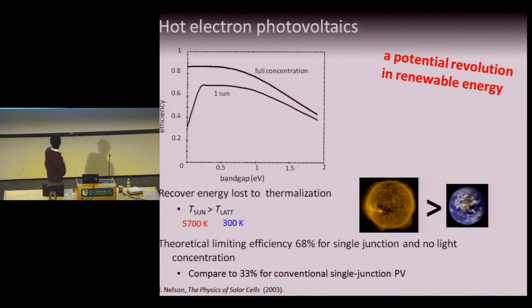So I'm going to this figure here, which is taken from Jenny Nelson's book, The Physics of Solar Cells. This is the go-to book if you want to learn anything about the basics of semiconductor physics and solar energy conversion. It shows you the theoretical limiting efficiency for a hot electron solar cell, plotted here as a function of semiconductor band gap. Although for the purposes of this discussion, you could more or less ignore this abscissa, and we'll focus on something like silicon. So I'll focus around one electron volt band gap, move up here, and you see for one sun, that means a planar structure looking up at the sky and seeing a sliver of 6,000 Kelvin and most of 2 pi at the temperature of the atmosphere, which is 300 Kelvin, the theoretical limiting efficiency for this technology is about 68%.